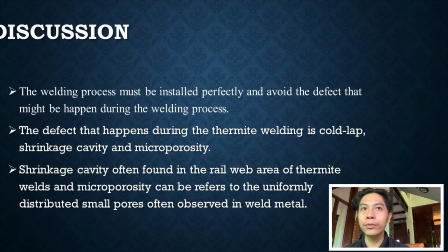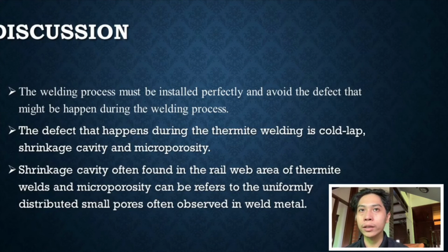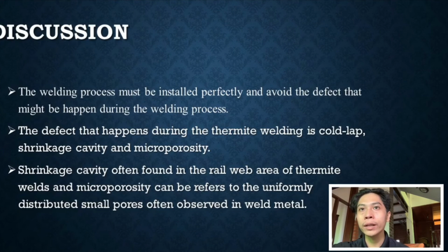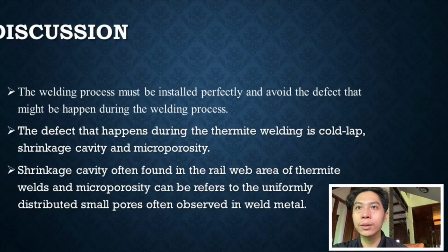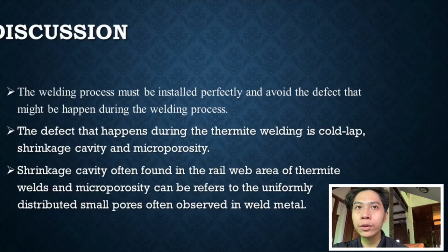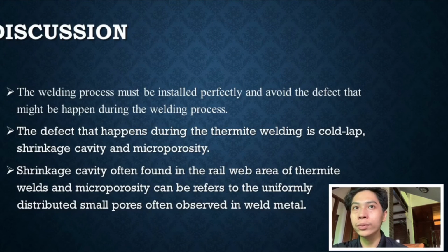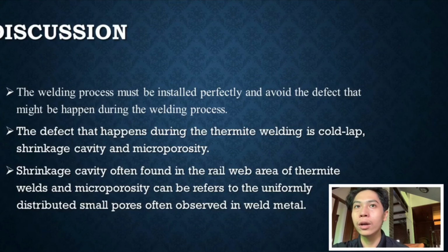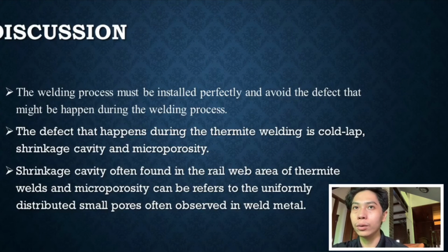Shrinkage cavity is often found in the rail web area of thermite welds, and micro porosity can be referred to as uniformly distributed small pores often observed in weld metal.